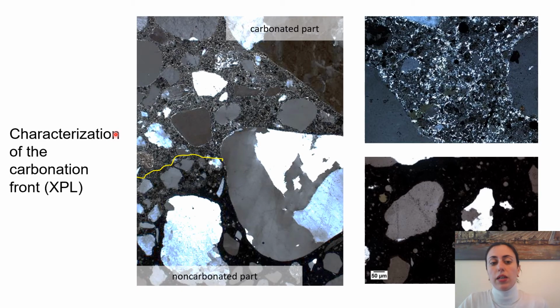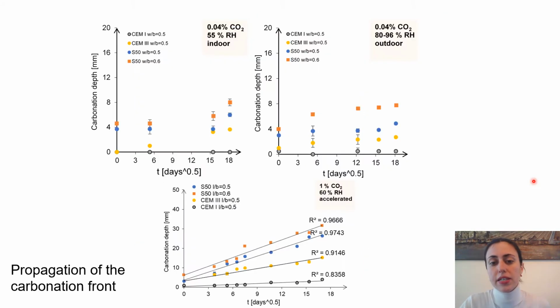Because of that, we also investigated the carbonation front with microscopy. Under cross-polarized light, we could observe the zone, or the front, between the carbonated part and the non-carbonated part. As you can see, in the non-carbonated area the microstructure is black because it is amorphous, while in the carbonated area, the microstructure is full of light small calcium carbonates.